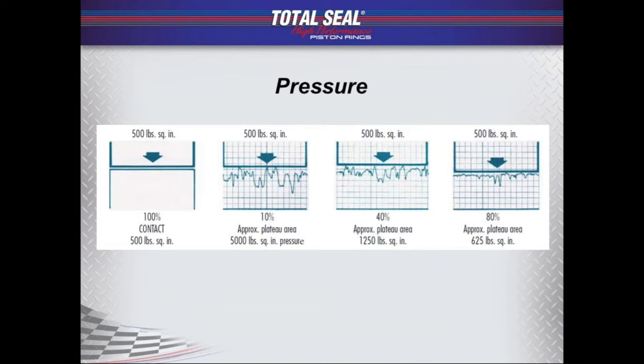It didn't have a lot of plateau, and through the running in process, again, the ring's naturally going to plateau that bore over time. We've ended up with all that material down in the pan. Well, that's prematurely worn block, prematurely worn ring, a lot of scuffing on the part, and almost always going to cause a delay or accelerate the wear process in the engine. As we come over to this slide, you've got about 40% plateau.